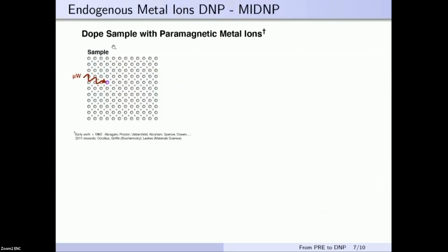What we do is we don't use exogenous nitroxide radicals. Instead, we dope our samples with paramagnetic metal ions, which upon microwave irradiation act as polarizing agents and are able to polarize the nuclei in the sample. Now, the main difference compared to the exogenous cases is that our samples are inorganic, unprotonated solids, so spin diffusion is going to be much smaller or even not present at all.